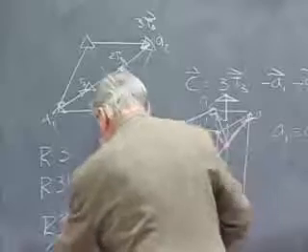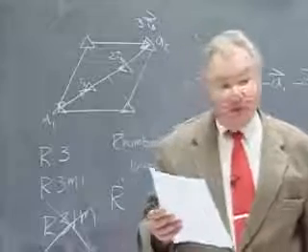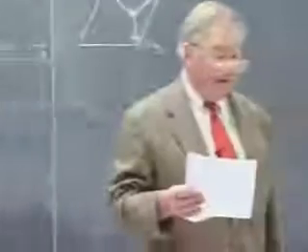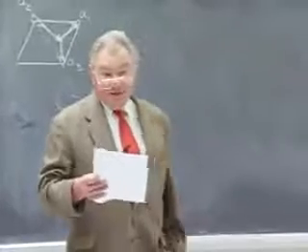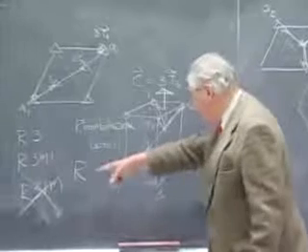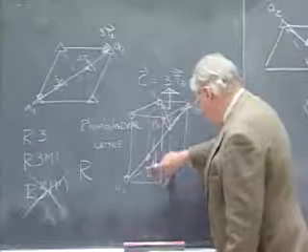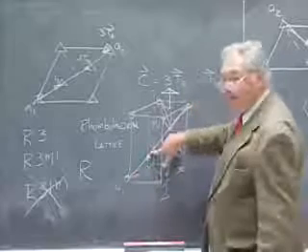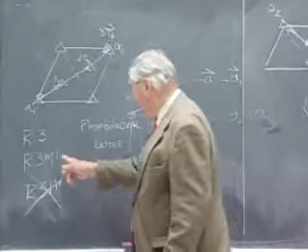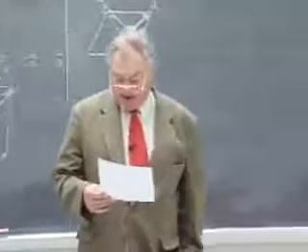That's impossible, because if you look at P31m, there is symmetry 3m at the origin and only symmetry 3 in the center of the triangles. So if I try to pick this as a third translation for plane group P31m, I'm taking symmetry 3m and plopping it down on top of symmetry 3, and that wrecks the plane group. So for the rhombohedral lattice, I can only have P3m1 or P3.